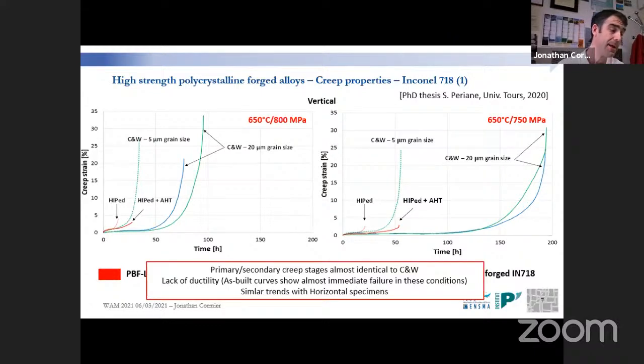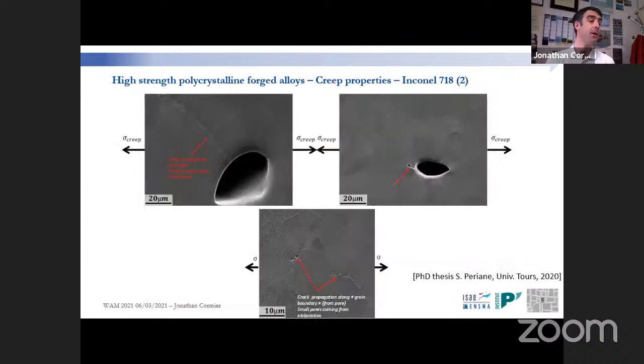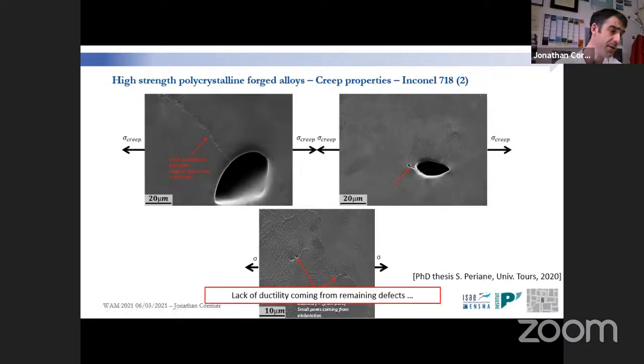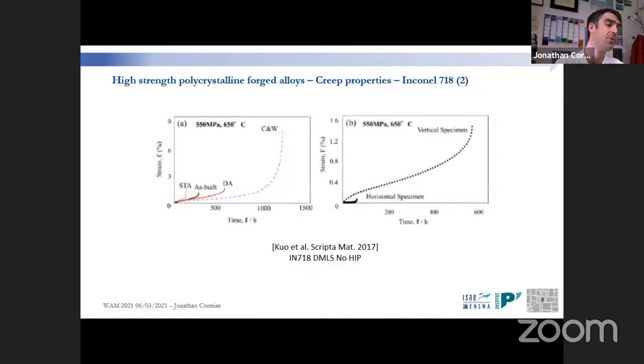And the main reason behind that, as you will see later on, is that even in the HIPed state, we always have some remaining small pores, where we have probably gas trapped within the pores, but they are serving as crack initiation sites, and they are limiting overall the ductility of the alloy. Moreover, we have been able to observe crack initiation at specific grain boundaries. I'm not showing this here clearly, but we understood that it is linked also to some oxides remaining at grain boundaries. And this kind of result is really typical in the literature.